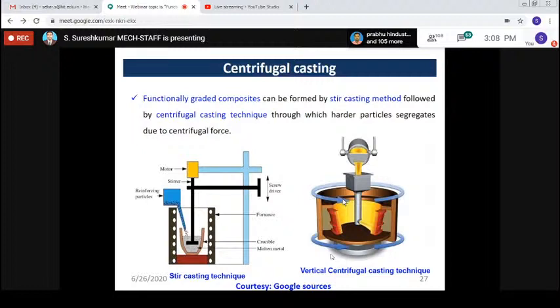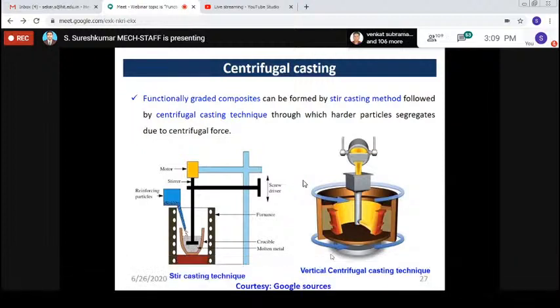So when you pour this mixture, obviously the reinforcement having the higher density will be sent out or pushed away, whereas the ductile matrix material is arrested in the inner region. So when you end up with the material, maybe a hollow cylinder, the outer region has more reinforced particles. The inner region of the hollow cylinder has more matrix than reinforcement. Again I am highlighting, the outer section of the hollow cylinder has more composite material.